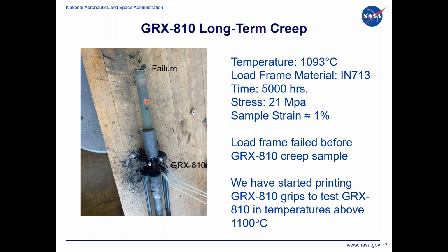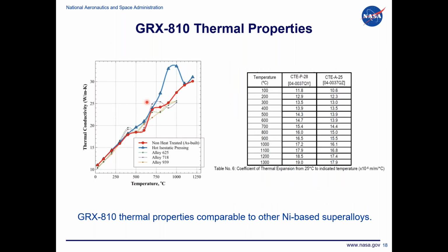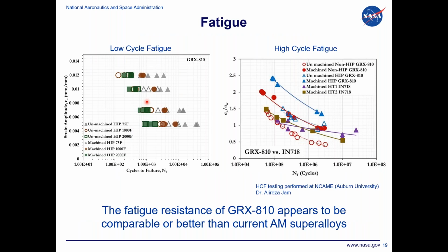MAR-M or Inconel 713s are either melting or falling apart in some of these environments. And so I feel like that really drives the point home. We've done a multitude of thermal property testing, CTE, thermal conductivity, and more or less have found in those instances that GRX-810 is comparable to a lot of these other superalloys that you would use. And so these nanoscale oxides aren't adding any showstoppers, especially in thermal properties here.